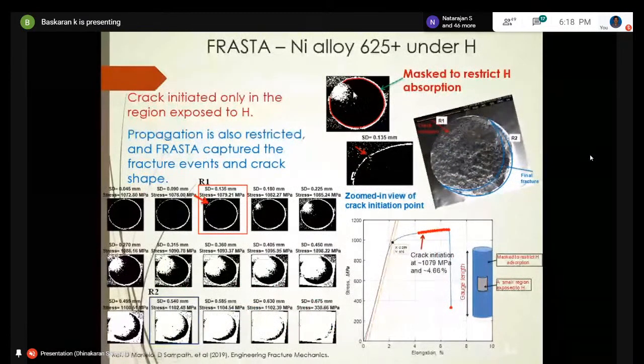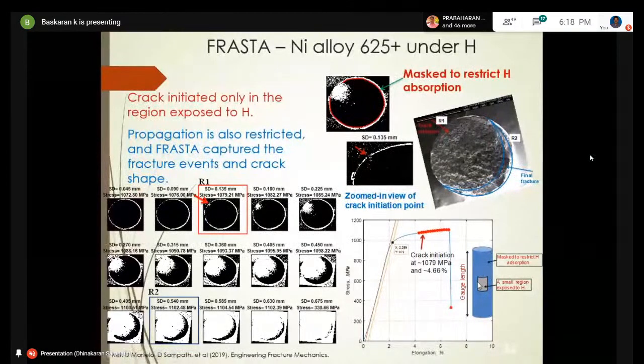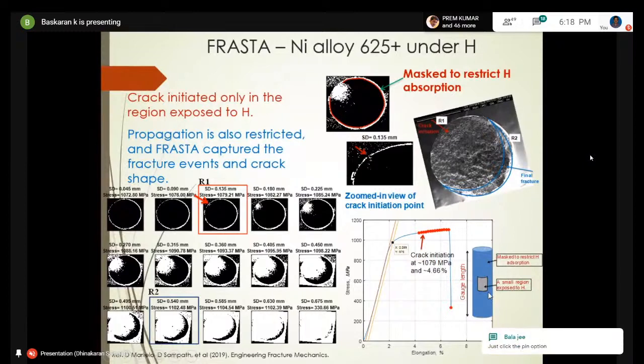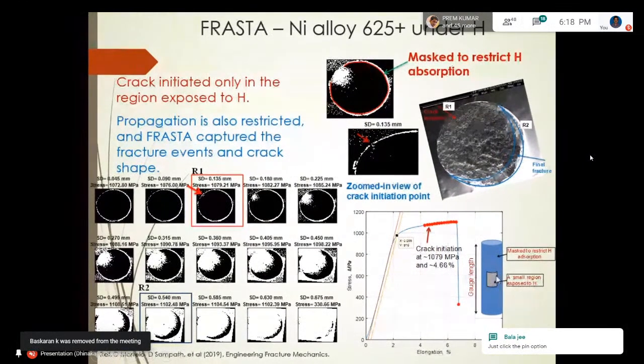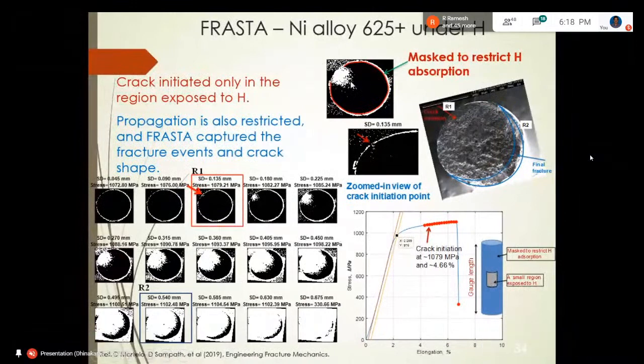And here we did a clever experiment using a different alloy, where this is the gauge section of the specimen, and we masked the entire gauge area except a small window which is exposed to hydrogen. And what we saw was the crack grew like a crescent.